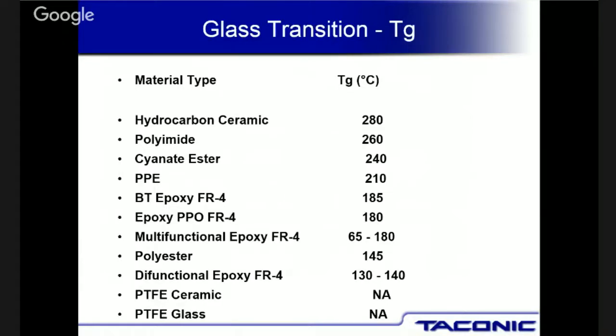And so that means, for example, the first one, hydrocarbon ceramic, can actually go up to 280 degrees C with a linear expansion. Above 280 degrees C, something else happens. Typically, the expansion goes up maybe five times the rate. And so you say, 280 degrees C, we're never going to see a board that hot. So typically, these are very good materials to use for high T sub G for a lot of different designs.